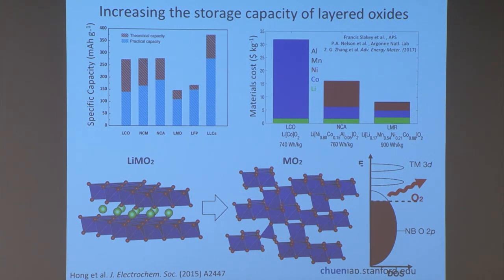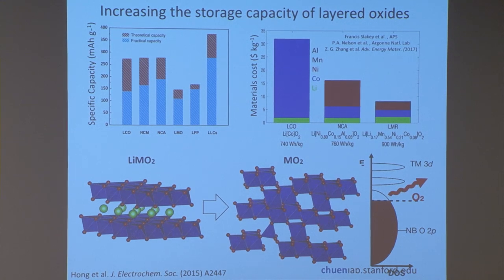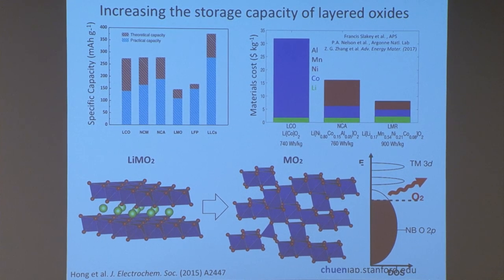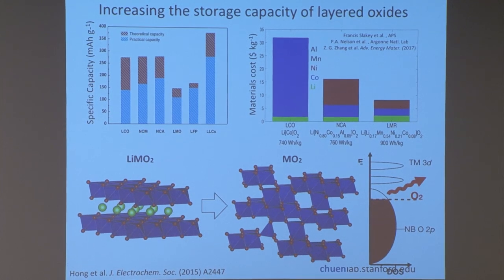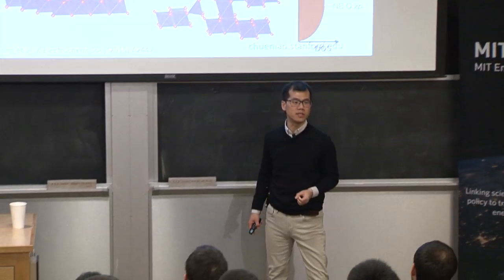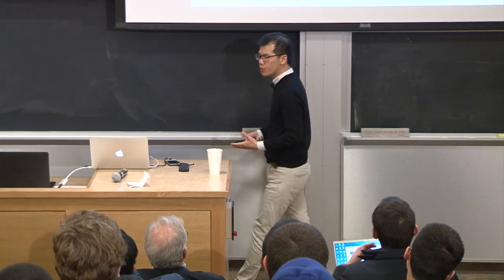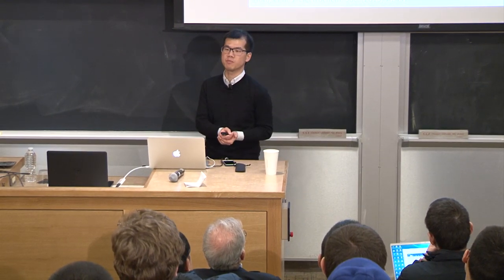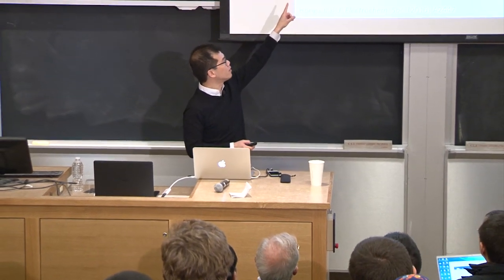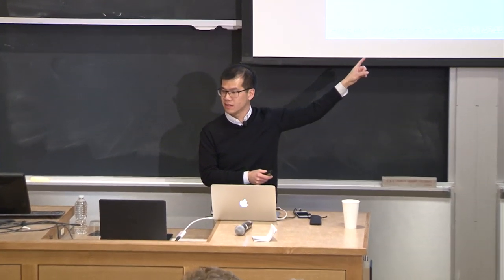Another major driver is, as you go to less expensive batteries, you also have to think about using more abundant elements. So you go from a cobalt-rich composition to a nickel-rich composition to a manganese-rich composition, and the cost can go down up to a factor of 4 in raw materials. So these are driving forces behind thinking about how to stabilize this material. So two things. One, prevent the structural rearrangement. Prevent the oxygen from leaving this material as you remove the lithium, as you oxidize the material, and try to use more abundant materials along the way.